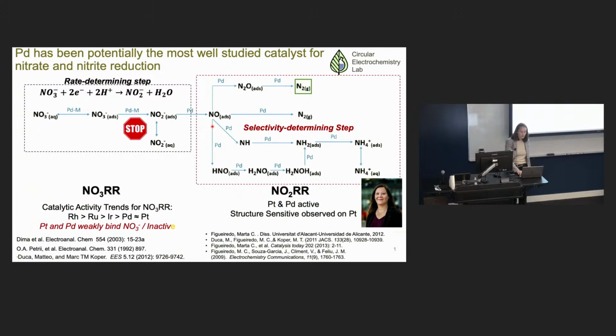But generally, researchers have found, and this is Marta Figueiredo, who is in the Netherlands and has done quite a bit of work on this, and really a lot of her PhD work pointed to the fact that palladium and platinum weakly bind nitrate, so they're not ideal for nitrate reduction, but palladium and platinum are very active for this second step, nitrite reduction. So basically, what people have found is that you kind of need two different materials, one that reduces nitrate and one that reduces nitrite. Palladium seems to work for nitrite. And then for nitrate, you can be looking at other materials like copper. Copper has been the most widely used for nitrate reduction.